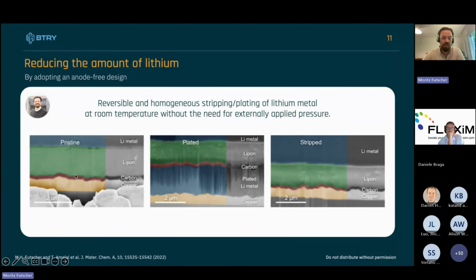So one interesting way is, first of all, to remove the lithium metal in the cell design itself, which avoids using lithium metal and fabricating lithium metal thin films. The other one is having an anode interface where this lithium metal grows and disappears homogeneously without this dendrite formation, without the risk of short circuits. And here you see part of the cell. So the copper in this case is the current collector. The LiPON is the solid-state electrolyte, which was developed by Oak Ridge National Lab. And then on top of that, we have lithium metal. And in the end, what we want to have here is the anode.